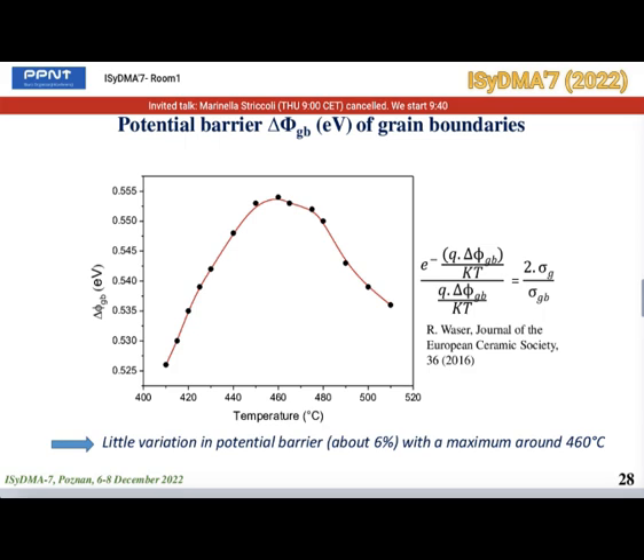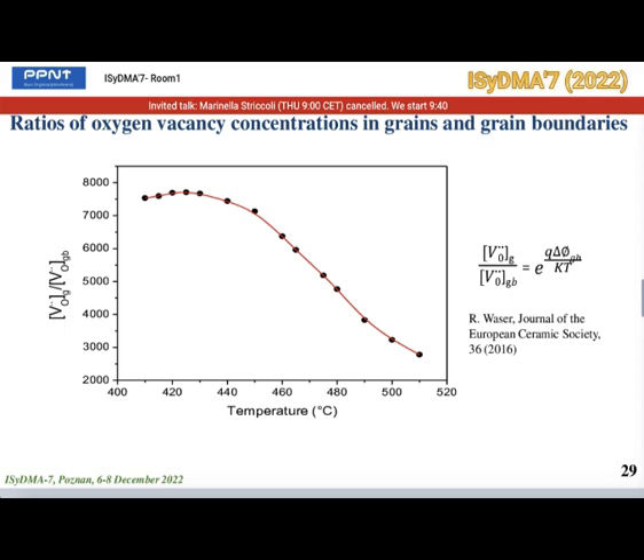We have calculated the potential barrier of grain boundaries. It can be calculated from the ratio of the continuous conductivities of grains and grain boundaries. It shows a little variation, about 6%, with a maximum around 460 degrees. Nonetheless, it is now possible from the potential barrier of grain boundaries to compute the ratio of oxygen vacancies concentrations in grains and grain boundaries.